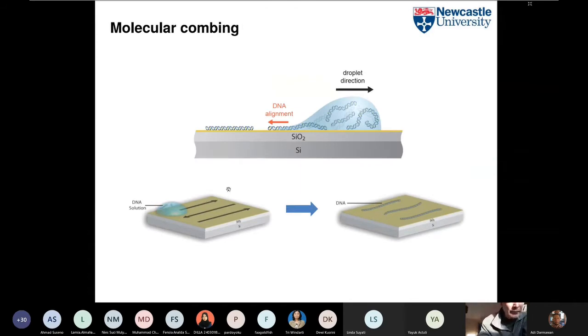Right, so the images I've shown are atomic force microscope images, and we usually make these by depositing a droplet of the dispersion in which the nanowires are prepared. So it's a reaction that happens in aqueous solution at room temperature, all of these reactions. We can take a small droplet, put it on the substrate that we use for AFM, and then we can drag the droplet. You can do this with the tip of a pipette, or you can blow it with nitrogen, or you can even simply tilt the sample so the droplet runs down the substrate. And when that happens, the DNA molecules are stretched out at the receding edge of the droplet, and this is why on these images they show as long lines, because you can stretch them out by this process, which is known as molecular combing.